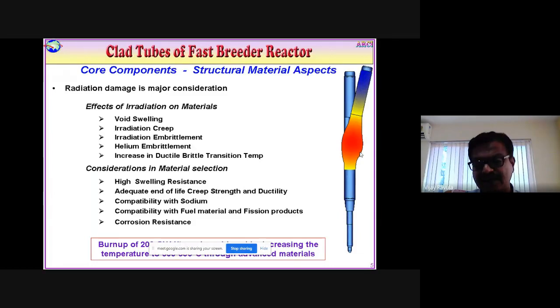You should have high swelling resistance and adequate end-life creep strength and ductility, because it should not break during handling of this radioactive material. At the same time, the material should have fewer active elements so that it does not become radioactive, since disposal of this material is also a big problem. Then compatibility, because this is all sodium cooled. Liquid sodium is used as the material to extract the heat generated by the nuclear reaction, and of course corrosion resistance and other things need to be there.